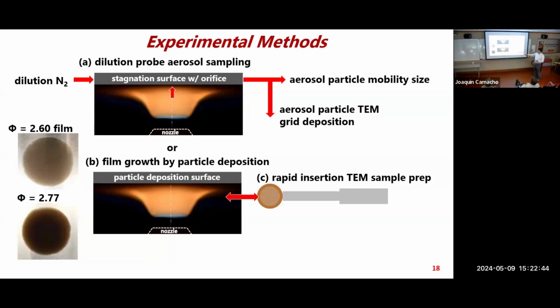What's interesting about these flames is that a typical equivalence ratio where you'll see soot flames is 2, meaning you have twice as much fuel as you need. 1 would be perfectly balanced. Typically, that's where soot starts to form: with twice as much excess fuel, you'll start to form soot particles. And mine is much higher than that.